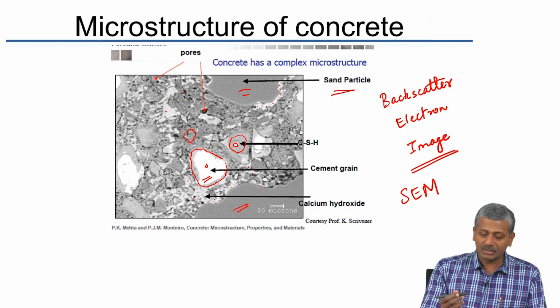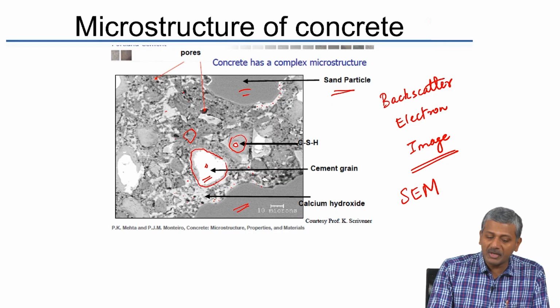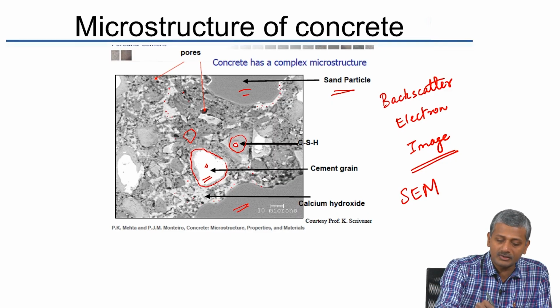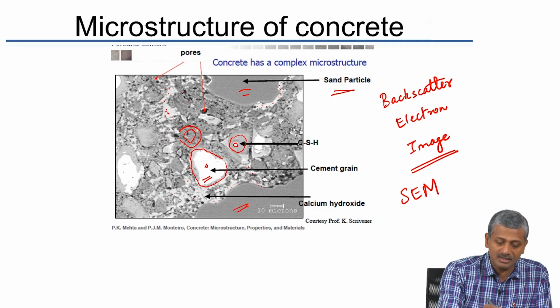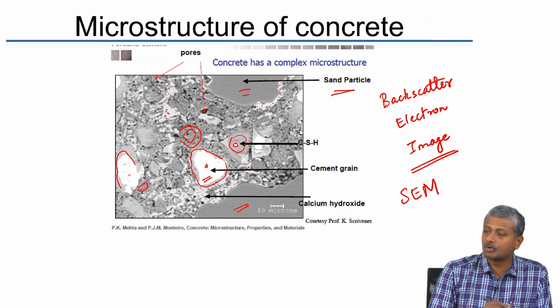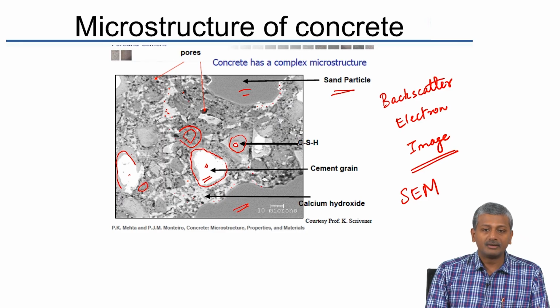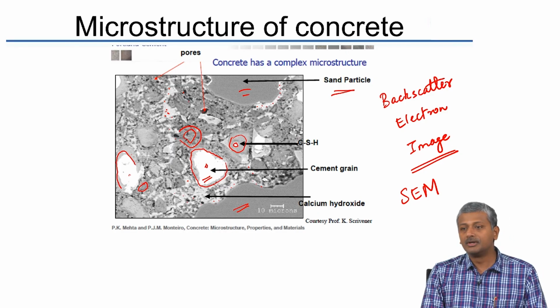So, this is a microstructure of the concrete. Now, if you look in the paste, I said there is already a lot of calcium hydroxide that is present. There are grey areas which are your outer CSH, and then there is inner CSH. Where is the inner CSH? Look at this cement grain here. Look at the layer around it, this grey layer which is surrounding it, which has a different shade of grey as compared to what is away from it. You can make out that different shade of grey, right. It is not very clear probably on the image, but I will show you more pictures to discern the color of the inner CSH and outer CSH.